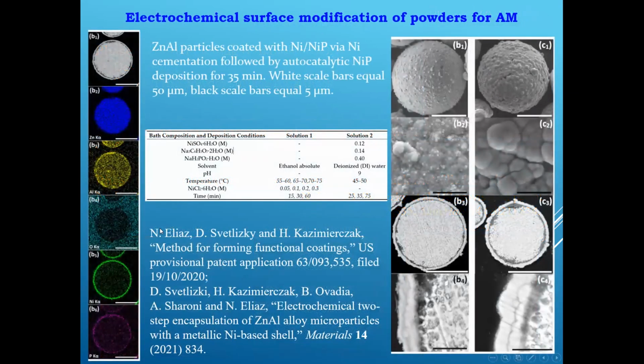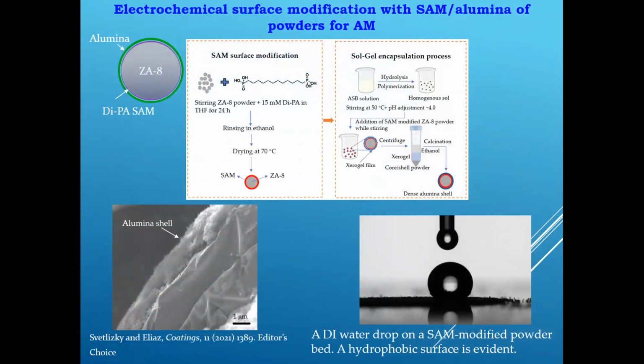So here you can see some examples of both the cross-section and top view, just to show you that indeed, and you can look on the left, B5 for instance, that we were able to form a good shell of nickel. You can see it also on the right side, microscope images. Then in terms of the effect on surface hydrophobicity, you can see that we successfully converted the very hydrophilic zinc aluminum powder into a hydrophobic surface with a contact angle of around 141 degrees, which was one of our goals.